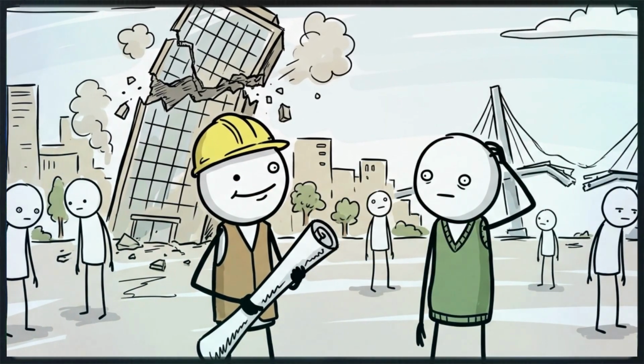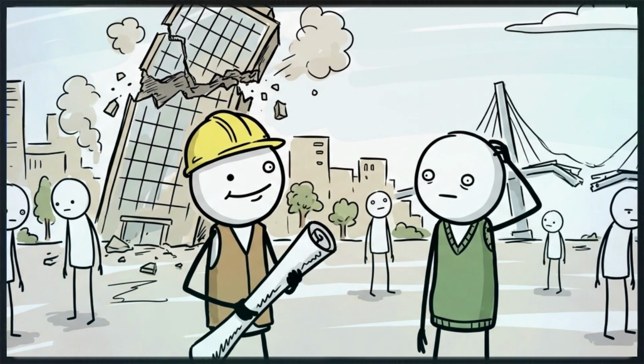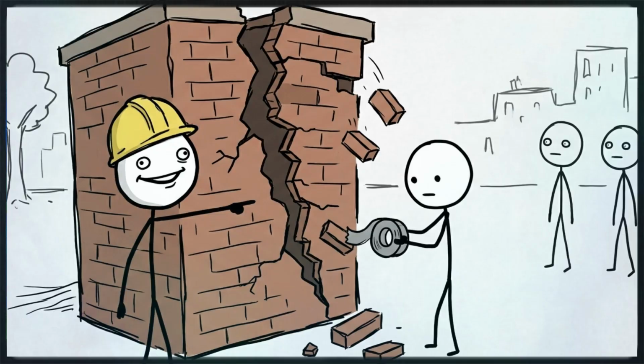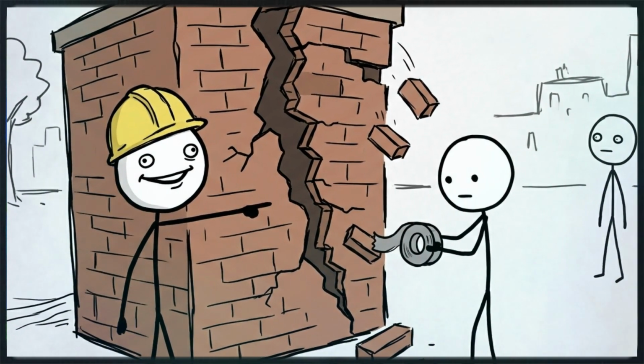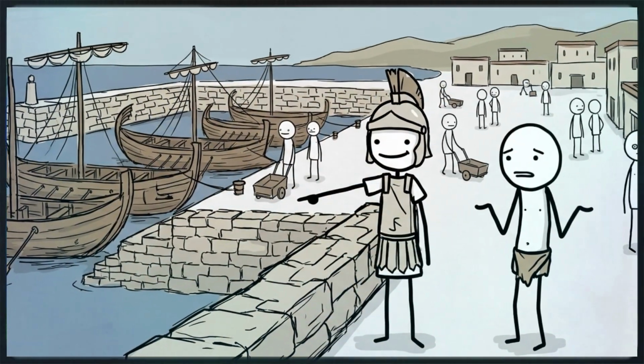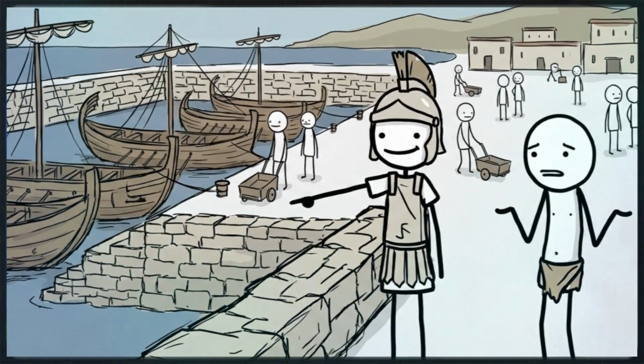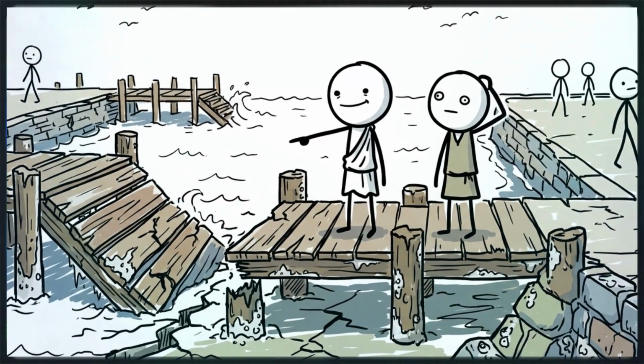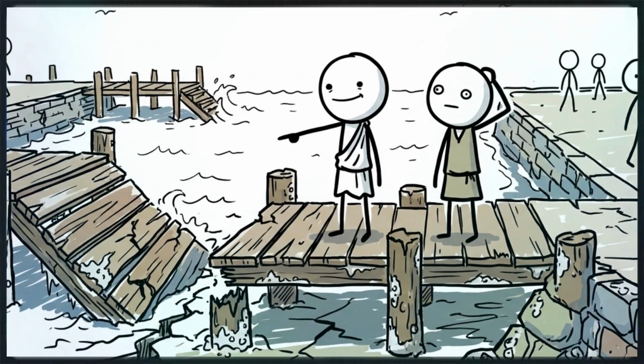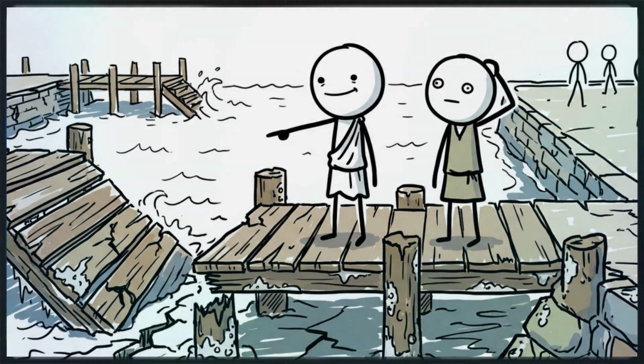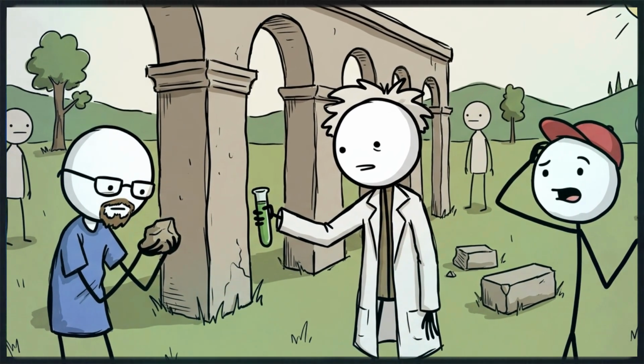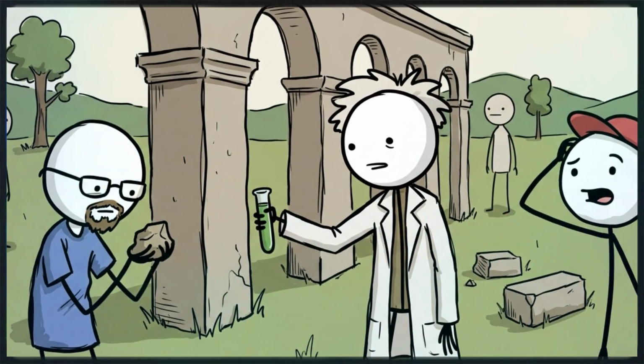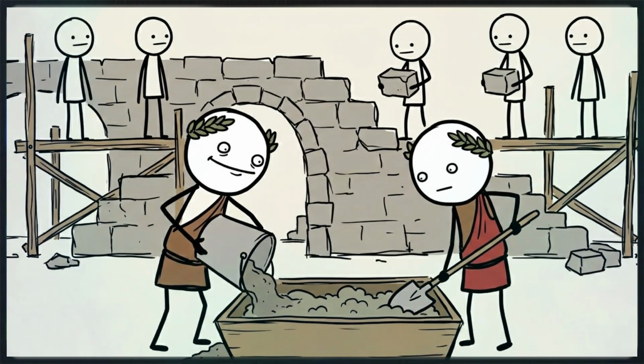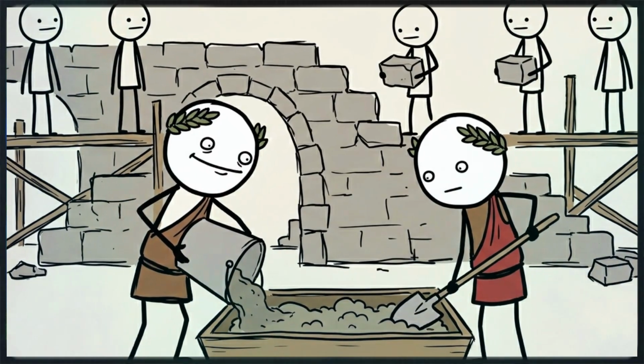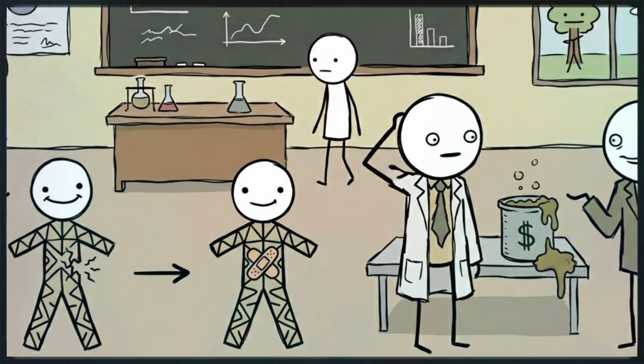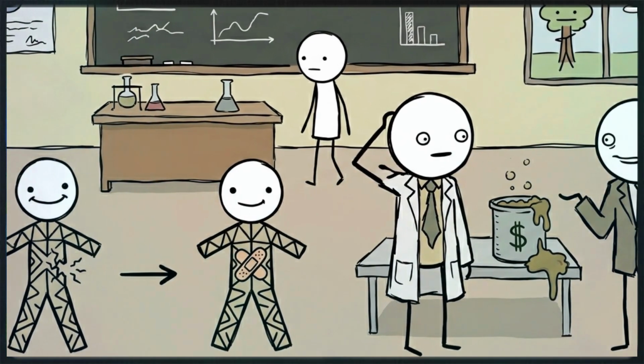Consequently, the lifespan of a modern bridge, skyscraper, or seawall is heavily limited, often requiring catastrophic structural maintenance within 50 to 100 years. Yet, across the Mediterranean coastlines, Roman harbors, breakwaters, and piers have been continuously battered by highly corrosive saltwater and intense seismic activity for over 2 millennia. Not only have they not collapsed, but chemical analysis proves they are actually growing stronger as the centuries pass. This is Roman concrete, opus caementicium, a chemical marvel and a dynamic, self-healing metamaterial that modern material science is still